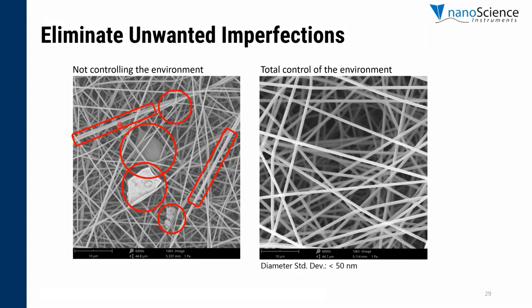So we are seeing fiber bundles. We're seeing fiber-fiber bonding. We're even seeing fiber beading during the process. And if you don't have a really tight and enclosed area, you're going to see dust forming in the sample. Meanwhile, when all parameters are tightly controlled, the microstructure that you obtain is consistent and reproducible every time.